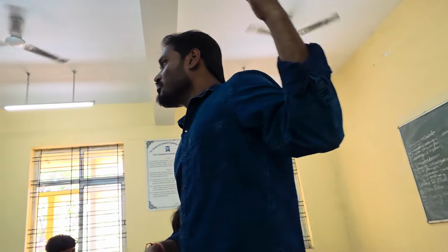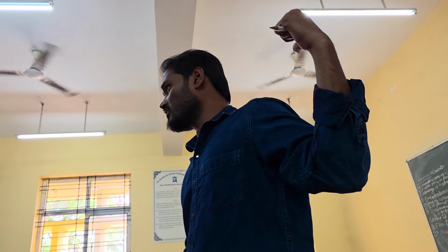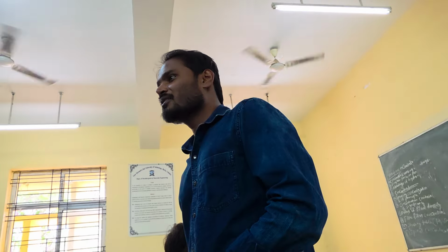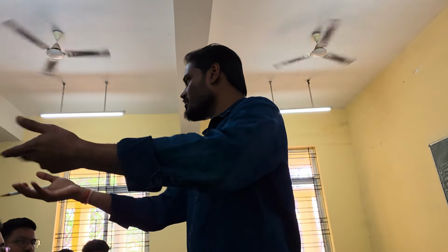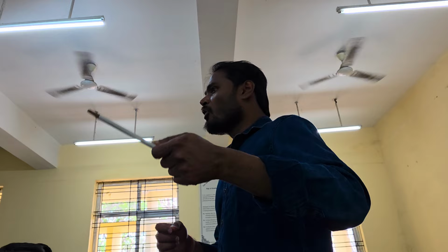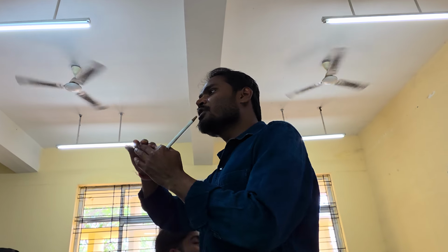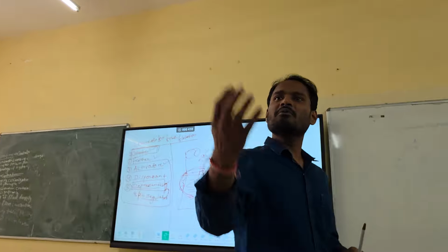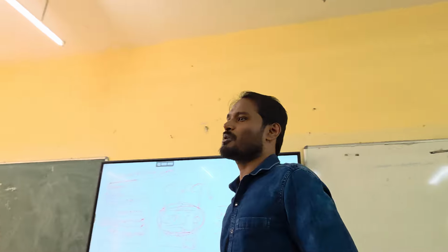But the point is, before that, in the concentration process, your slurry is acidic. Listen carefully. Because you have done leaching with acid now, finally the slurry will also be acidic. Yes or no? Your slurry will be acidic. And you want your collector to work properly, but the collector may not work in the acidic medium. You need to increase the pH value. So what can you do? You just add lime. Lime is basic in nature. If you add lime, it will increase the pH value. Now the collector will work properly.